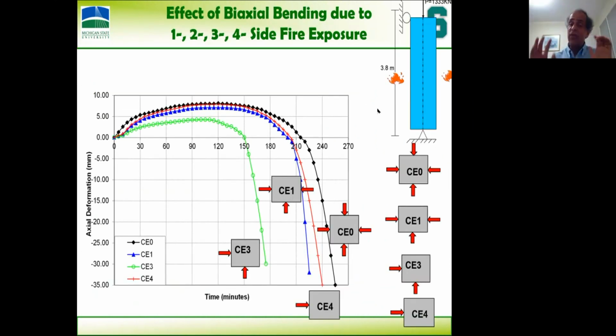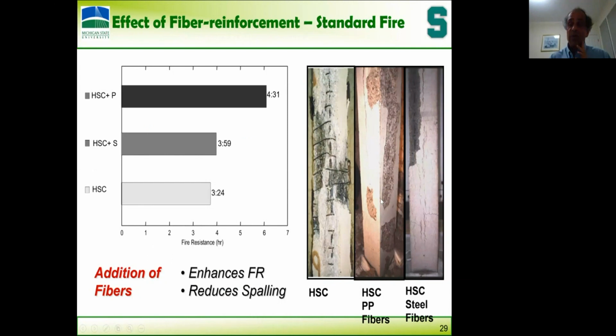How can you overcome this? If you add polypropylene fibers, these fibers are 0.1 to 0.2% by volume. They melt at early temperatures of 160 degrees and increase the permeability, or create pores where the pore pressure can easily be dissipated. If you add steel fibers, it increases the tensile strength and it significantly overcomes the pore pressure. It withstands the pore pressure so that there is very little spalling. Okay, you can do a few other things.